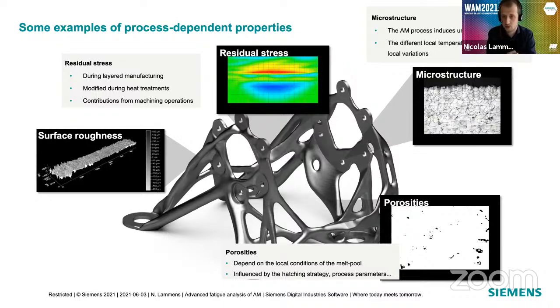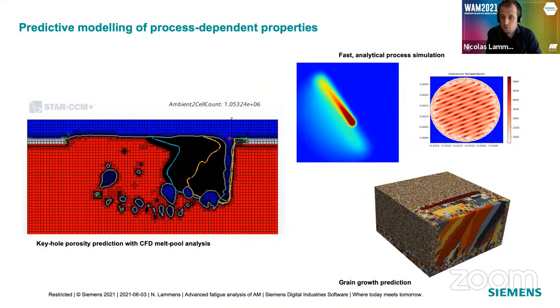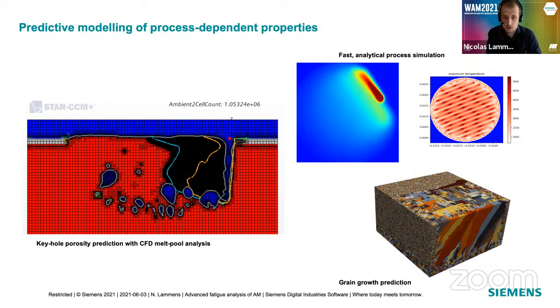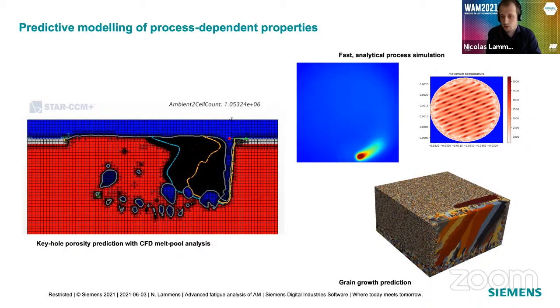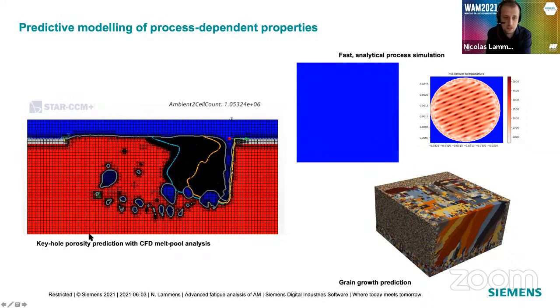So it's important to take into account that all of these properties that I mentioned here and many others are not a global property of the component, but a very local property that fluctuates throughout the entire component. And what we try to do then to be able to predict how all these properties are going to affect fatigue life is to build predictive modeling simulations that allow us to predict some of these features. And for example, we do CFD simulations. That's a picture you see here on the left, where we could try to predict keyhole porosities during the printing just based on the process settings.